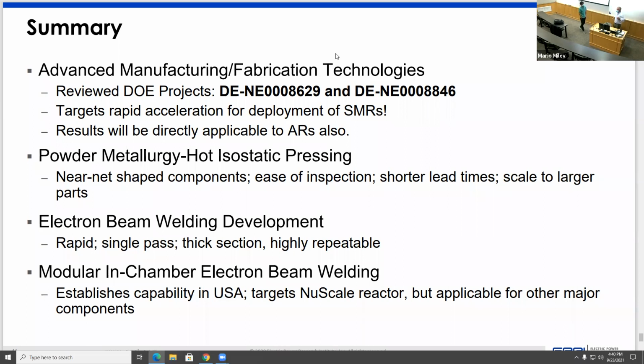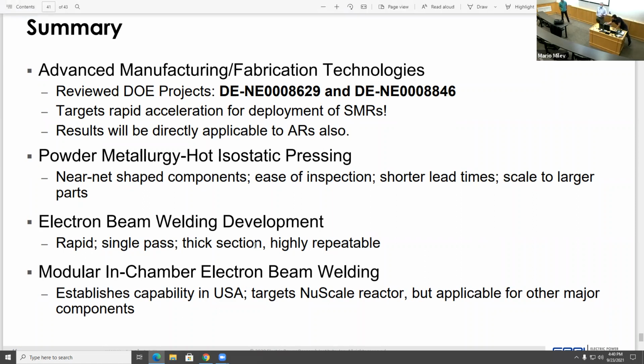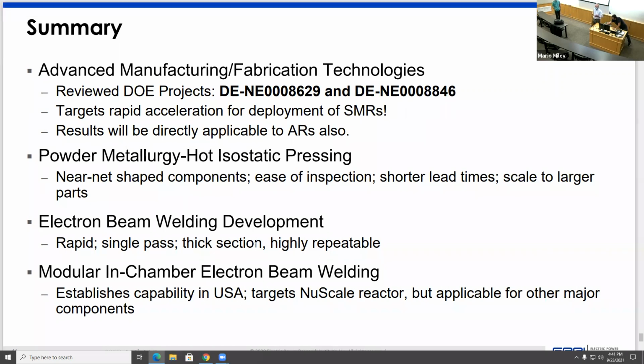Yeah, that's a good question. Does the PM-HIP process result in a crystalline or an amorphous structure? It's a crystalline structure. One of the reasons we're looking at it is because when you put a powder in a hot isostatic press and it consolidates, it results in a very uniform equiaxed structure. So you can push sound through it easily from whichever direction you're trying to look at it from. So we can use ultrasonic processes to understand, do we have anomalies or flaws in that component?